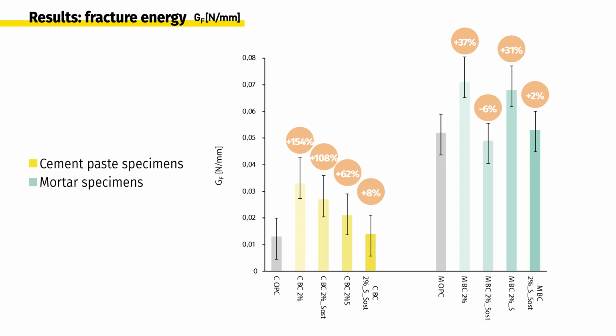Respect to the biochar used as a substituent in the mortar mixes, there was a slight increase of 2% when the biochar was mixed with the cement powder and a loss of 6% when it was mixed in the water and superplasticizer solution.